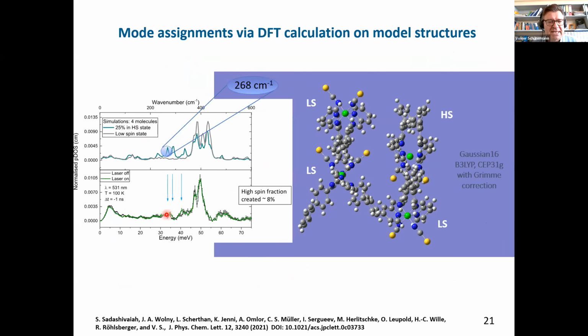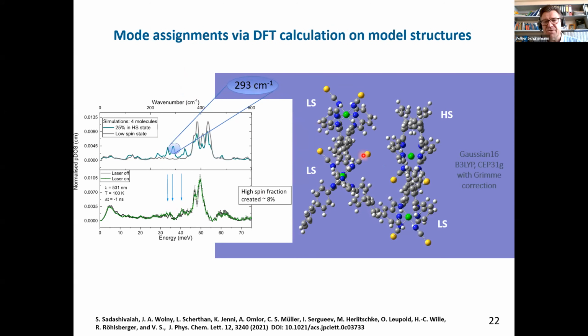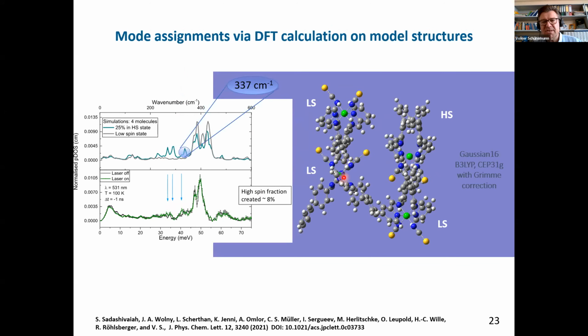Here's the analysis. We see definitely changes which are small, 8% excitation, but that's also usually the case in pump probe experiments, people told me. And we could actually measure or determine these bands here where the high spin is excited, or the iron is excited to the high spin state, moving. Here the other band at 293 reciprocal wave number, another molecular mode occurs. And this mode is most interesting because here a low spin iron is moving. The high spin, which has been excited, is not moving. And we think this has a functional role in the self-amplification process.